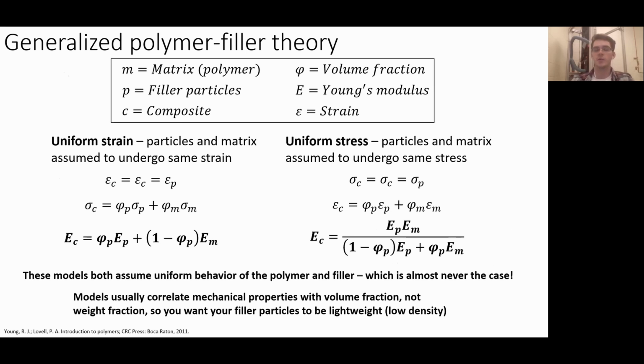So here is some of the generalized theory for polymer filler composites. This is a really broad overview of 2 main assumptions we can make in order to get a model for the Young's modulus. On the left here, we have the uniform strain assumption, which, as the name implies, assumes that the particles in the polymer are undergoing the same strain. And so that gives us the rule of mixtures, where the Young's modulus is equal to the weighted average of the polymer modulus and the particle modulus.